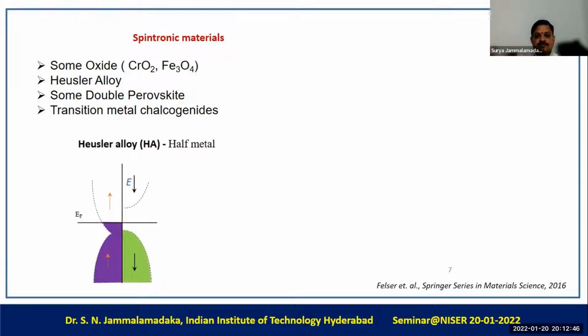Now, if you look at Heusler alloy materials, they have been found to show a variety of magnetic properties, and they also show half-metallic nature. If you look at the band diagram of the Heusler alloy material, it acts like a conductor for one spin polarization and an insulator for the other spin polarization. For the down spin, it will act like an insulator. For the up spin, it will act like a conductor.